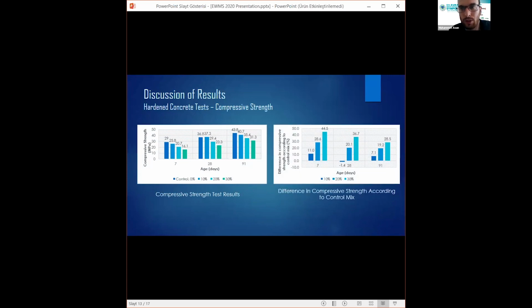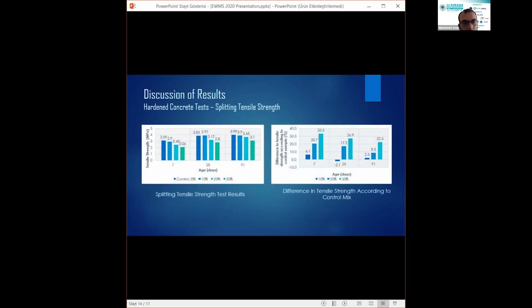If you look at the compressive strength test results, at the end of 7 days, the strength loss of concrete containing 10% glass powder compared to the control samples was 11%, while at the end of 91 days, the difference was reduced to 7%. The tensile strength of samples behaved similarly to the compressive strength. At the end of 7 days, the tensile strength loss of concrete containing 10% glass powder compared to the control samples was 6%, while at the end of 91 days, the difference was reduced to 2%.